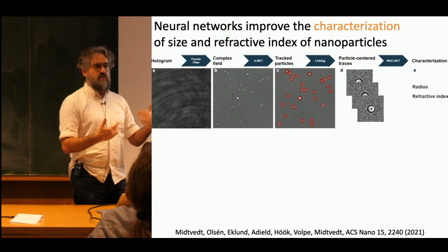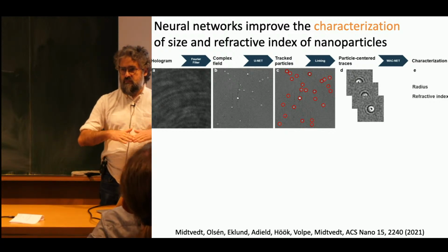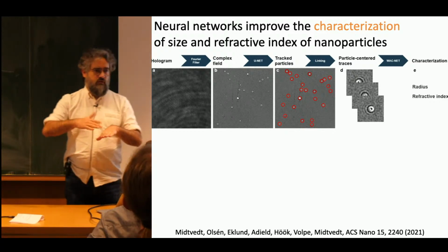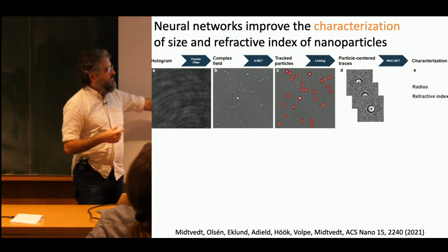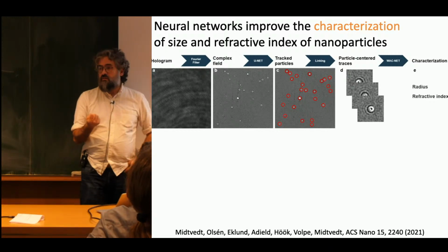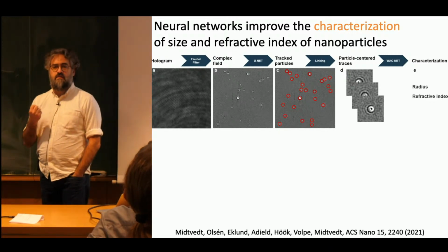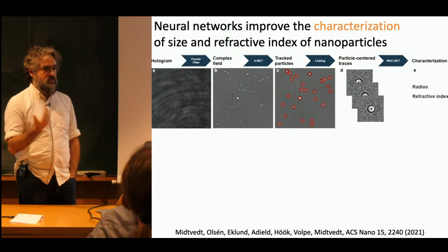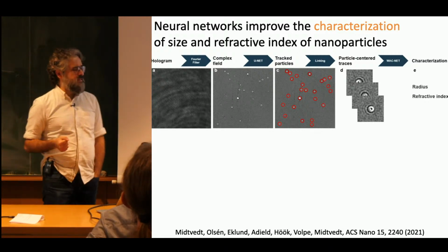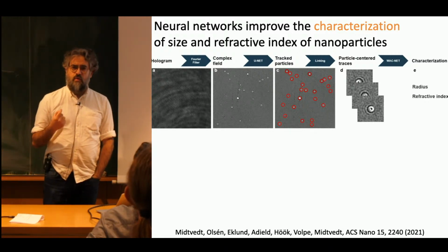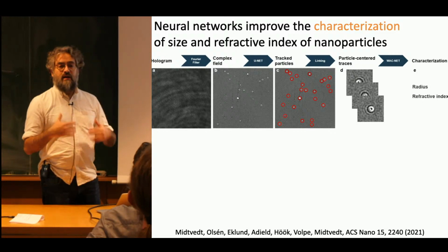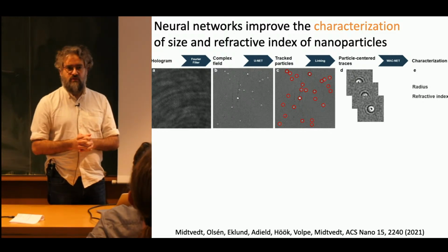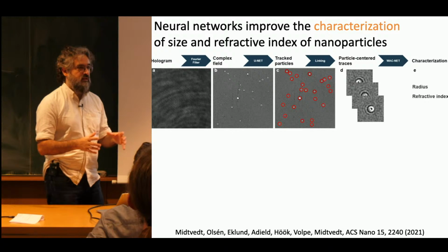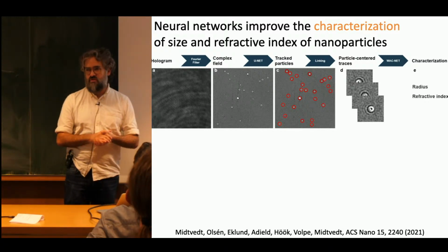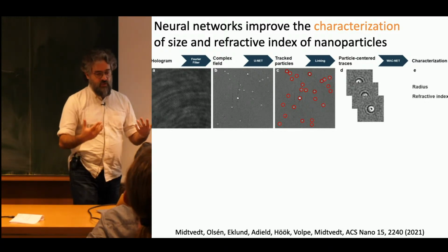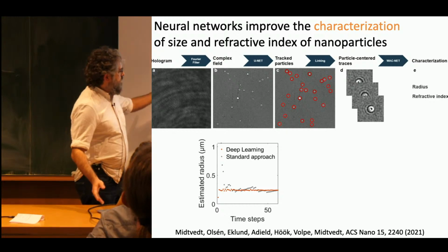Having an image, which in this case was a holographic image generated by a holographic microscope. Well, to do this, we need to train the network. Again, we want to train on simulated images because it's much more robust. The problem is that in this case, we had to reconstruct a digital twin of the microscope, in a sense, which permitted us to simulate the images under the same conditions, including all aberrations and so on. And by doing that, we managed to have a very, very good result.